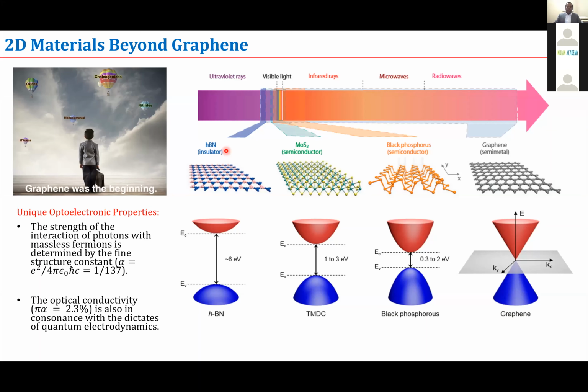Similarly, for boron nitride, you can have cubic forms of boron nitride. You have hexagonal forms of boron nitride. You have also turbostratic boron nitride, amorphous boron nitride. However, the hexagonal form of boron nitride is actually two-dimensional. It is a layered structure. Other forms of boron nitride are not. Just like diamond, in the case of carbon, it's not a two-dimensional material. It's not at all sp2 hybrid. It's sp3 hybridization.